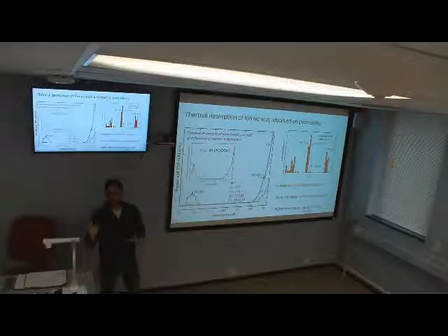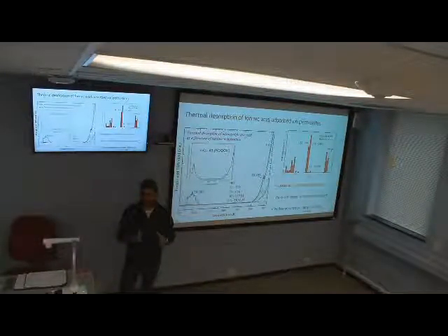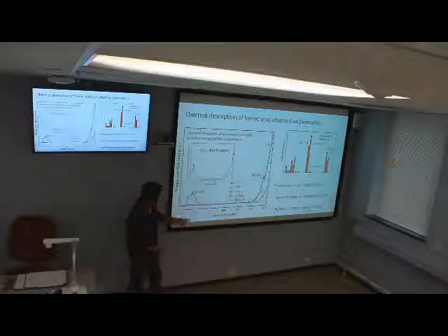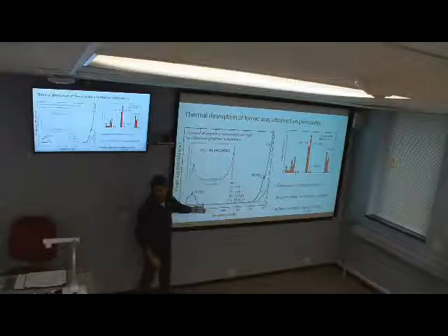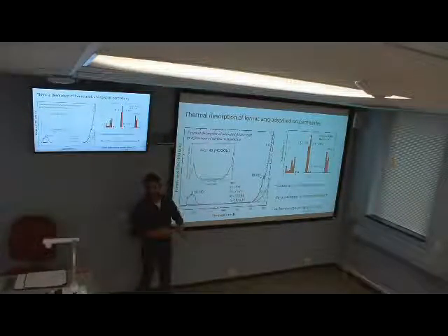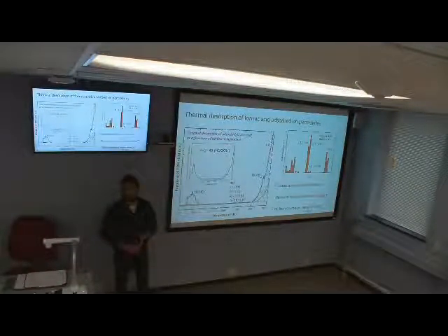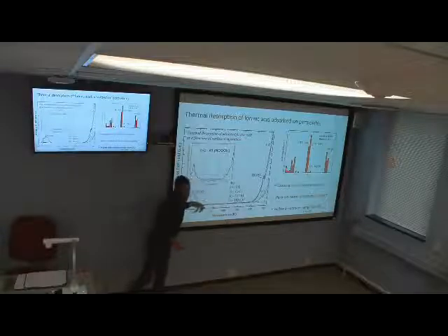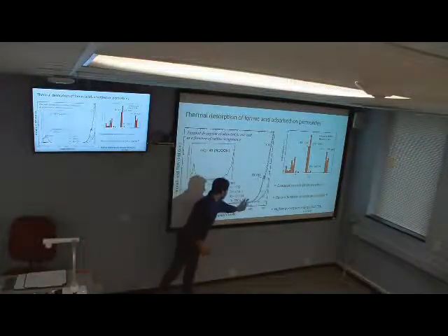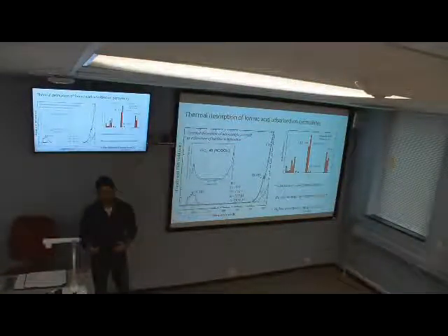And also we adsorbed formic acid on the lead iodide films just to see whether there is any effect of lead iodide. On lead iodide we don't see these high temperature peaks, we only see the lower temperature peaks. So on lead iodide, formic acid adsorbed somewhat molecularly. On lead iodide and ITO substrate, we tried both, and it has peaks below 400 Kelvin, not this kind of high temperature. So that means formic acid binds strongly to the perovskite layer.